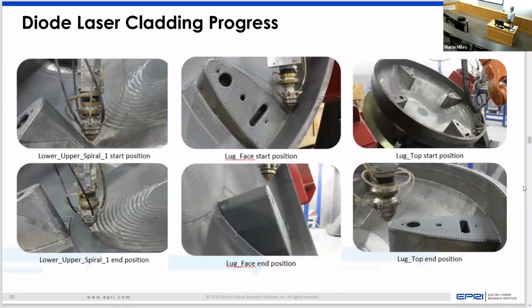So normally when you manufacture a component, a large reactor vessel, you will want to clad the inside surface of those components for corrosion performance. They're either clad with an Inconel, a nickel-based alloy, or probably a 308 or 309 stainless steel, which again gives them the corrosion performance on the inside surface of the vessel. Normally, we've used submerged arc welding or electroslag welding, which puts down a very large bead. It's all semi-automatic at best.